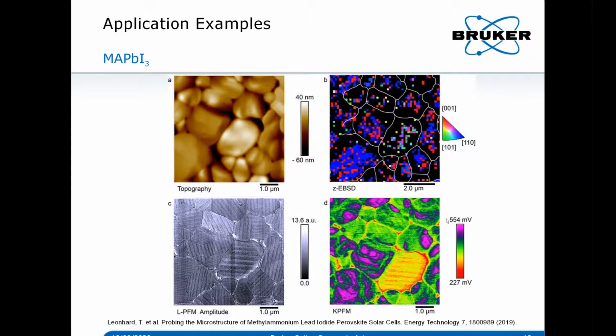And the same thing, actually, we notice that the domain distribution for this specific grain is slightly different from the other one. Specifically, this domain in this grain is actually wider than the other one. Then if we combine it with the KPFM, which detects surface potential of the material, we can see from the KPFM we also see this kind of distribution, which give you some basic